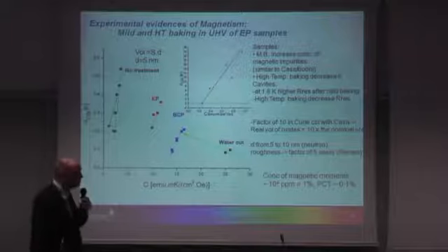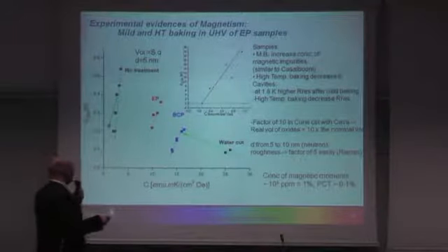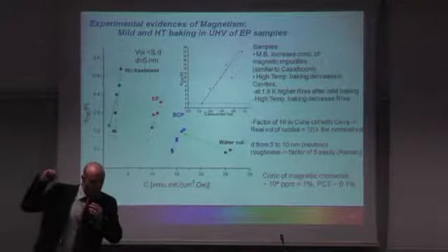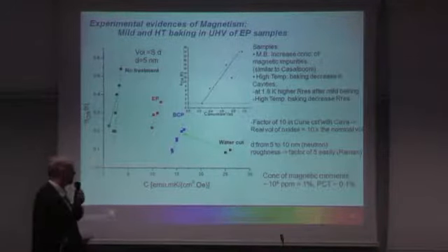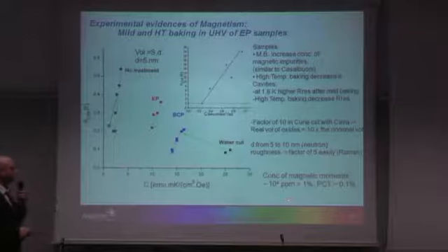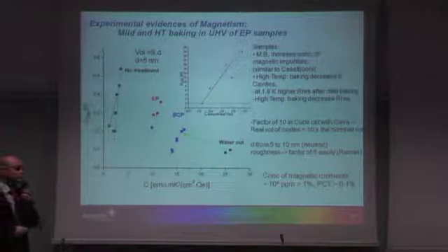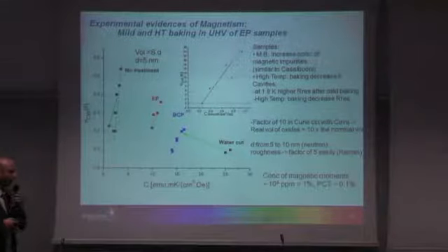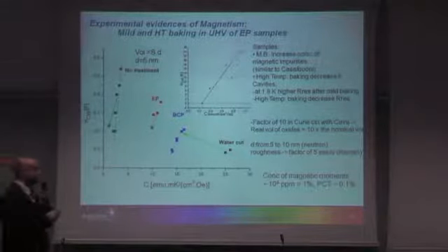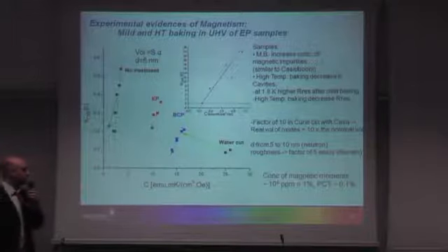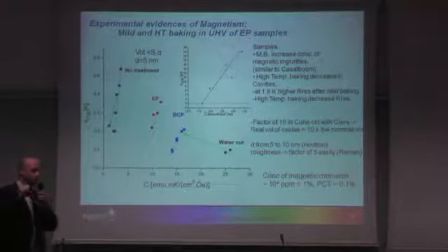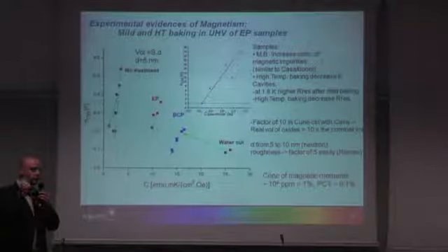So basically all this to say that a factor of 10 is easily achievable between that atomically flat 5 nanometer thickness and the real volume of the oxide, which would mean it comes only from the oxide. And these are magnetic impurities in the oxides, which correlate with what I showed you before. If you estimate a concentration, you have roughly 1%, whereas the point contact shows more or less 0.1%. But this is somehow normal. This is measuring the whole volume.